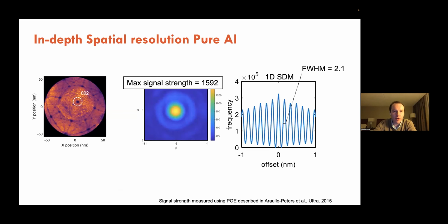So just a few quick notes on in-depth spatial resolution. I mean, it's looking pretty good. We weren't really expecting it to be particularly better than the previous platforms, but we wanted to check that we were getting reasonably good spatial resolution, and at least in depth, it looks quite good, at least comparable to what we're getting on the LEAP instruments when you're getting these crystallographic features within your detector map. So I've just done a Z or 1D spatial distribution map of the corresponding reconstructed region here. So we're histogramming the interatomic distance, and you can quite easily pick up the lattice planes there. So that's looking reasonably good in that sense.